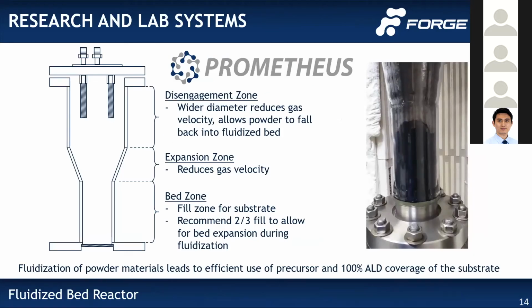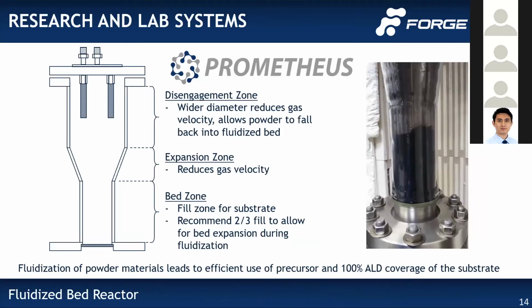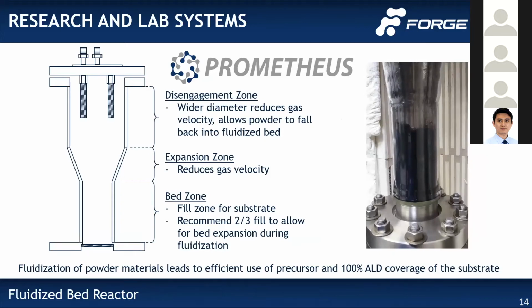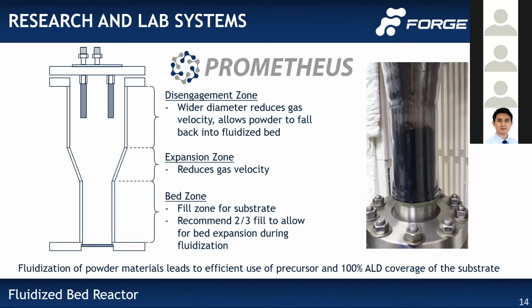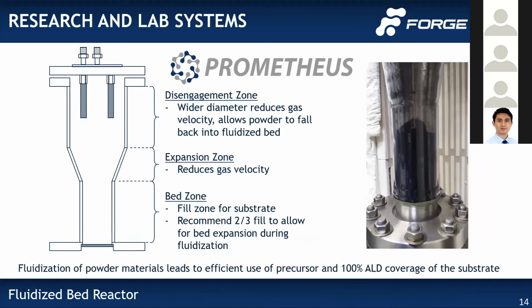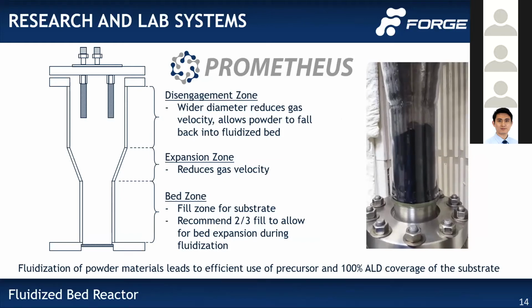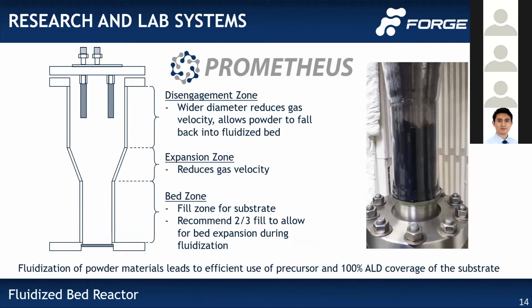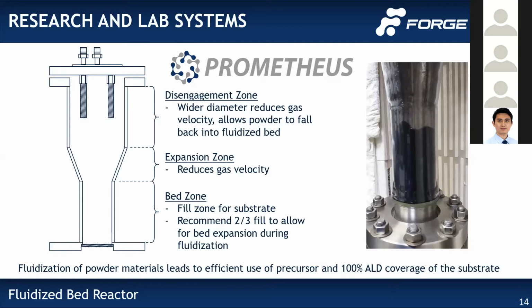So in our R&D systems, when we do particle ALD, most of that is done in fluidized beds. If you look on that right, the video is a fluidized bed. You have gas flow coming up from the bottom. It's a rendering here on the left-hand side. You have a porous frit on the bottom that holds the powder within the reactor chamber, and then frits on the top to allow vapor to leave the reactor.